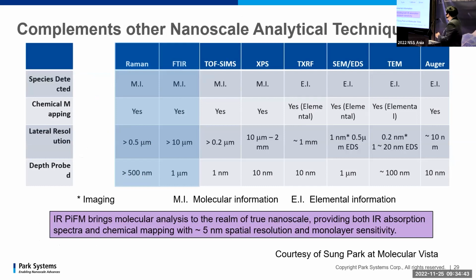it has really good elemental information detection, with a 0.2 nanometer resolution. But even with the same element, depending on the structure, it becomes a whole different molecule. That's why we need molecular detection. One good candidate for molecular detection is TOF SIMS, which has about 200 nanometer resolution, but it's not easy to use. The most widely used technology is FTIR, but the problem is that the scale is 10 micrometers. So people are looking for another solution, another technology for chemical identification.